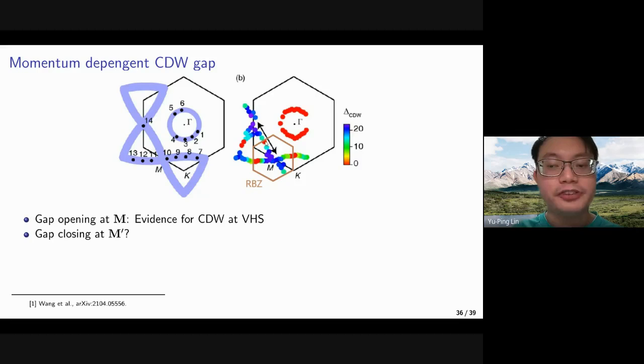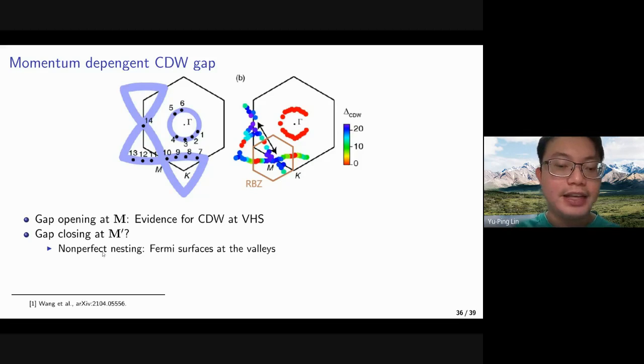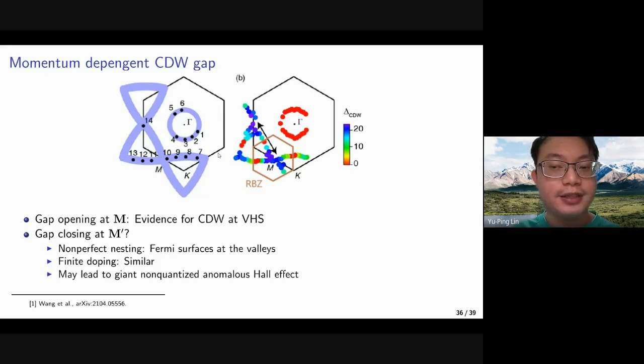So we also observe some kind of gap closing or nearly gap closing at the M prime points at the edge center of the reduced Brillouin zone. And it may indicate that it might be related to the non-perfect nesting, where we could have some Fermi surfaces around the valleys at the M and M prime points, so that if we have charge density wave, it will be gapless. It may also have similar effect if we have finite doping away from the Van Hove singularity. And this kind of effect, that is the presence of some Fermi surface, may lead to some giant anomalous Hall effect, which are not quantized.